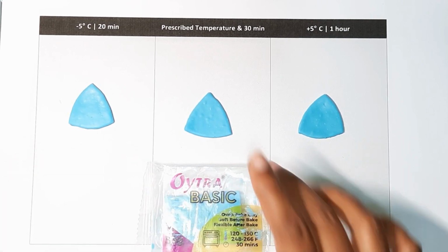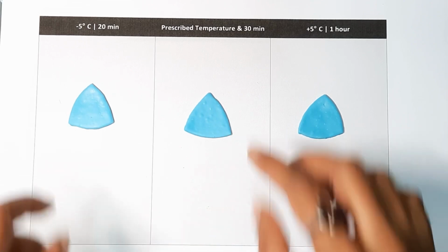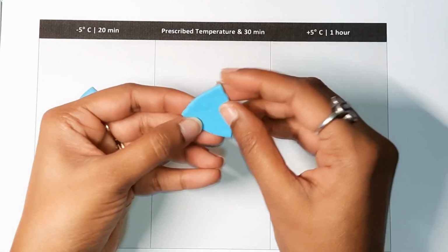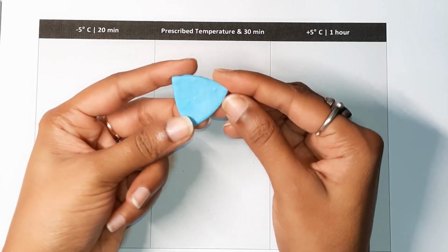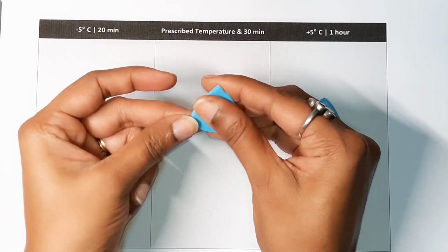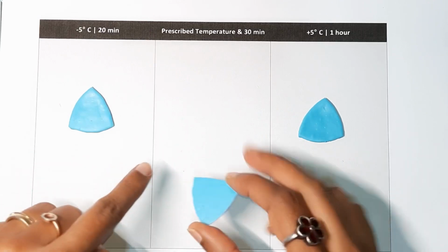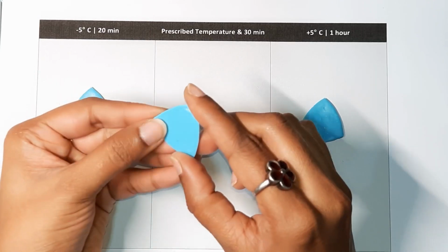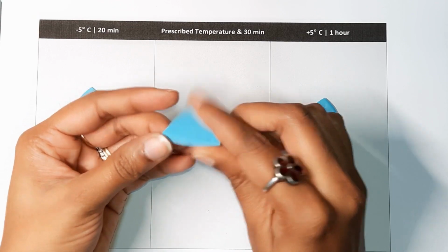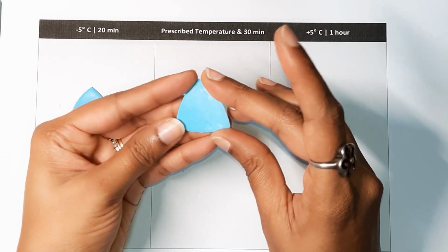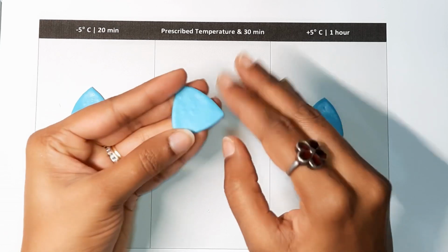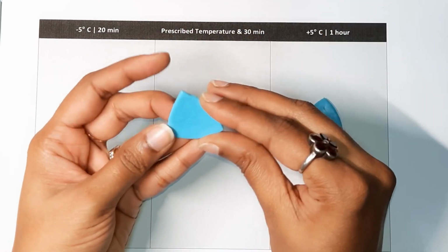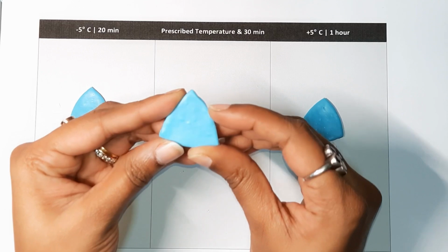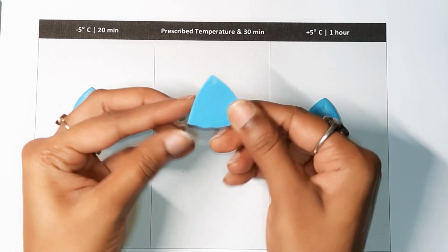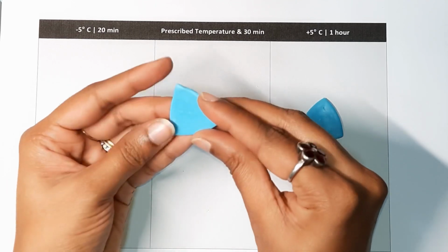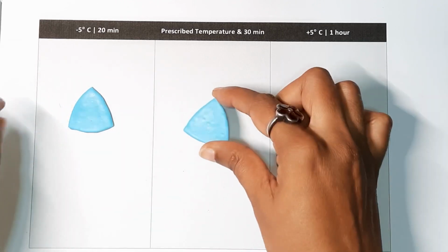at varying time frames. So if I look at the quality of this particular clay, it does tend to bubble. There are bubbles in this no matter what variant or how much I baked. It does tend to bubble. But if you look at the back side, there are no bubbles. So I think if you place a tile on top of it, you can reduce the bubbles for flat pieces. The back side has no bubbles. So that is one thing.